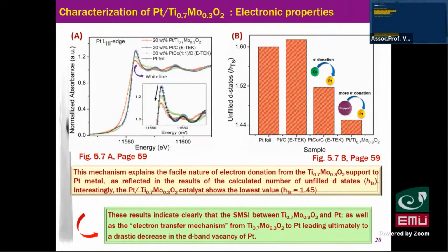Very interesting - for this research we think this is the first mechanism we found for non-carbon support. For carbon-supported platinum, the carbon plays the role of a support for platinum dispersion on the surface, without any chemical reaction or strong interaction - just a very weak interaction between Pt and carbon. Pt just disperses on the high surface area, highly porous carbon.